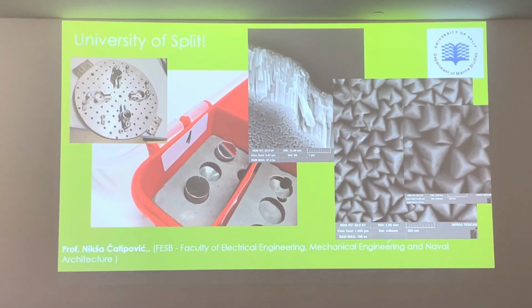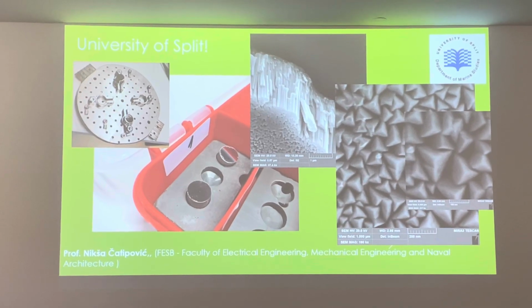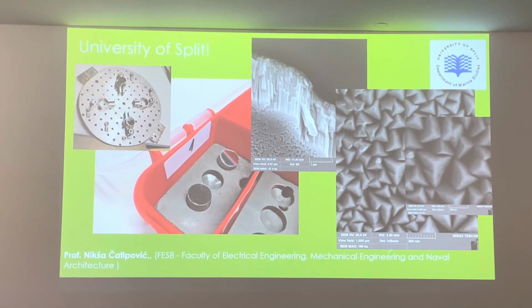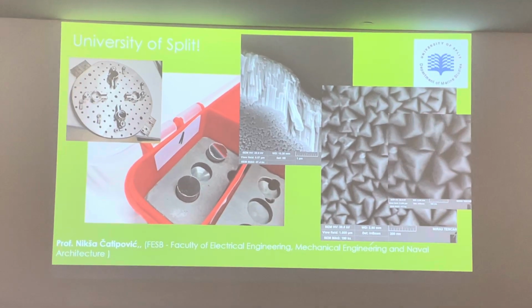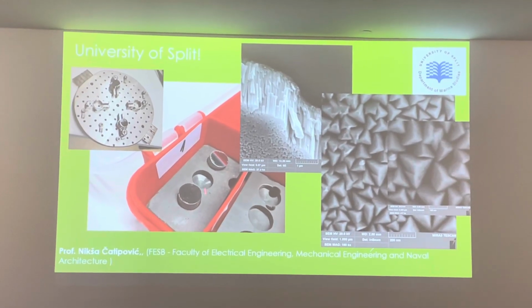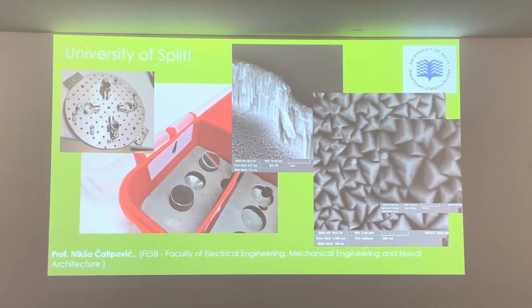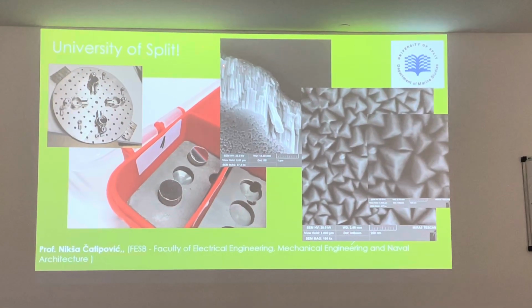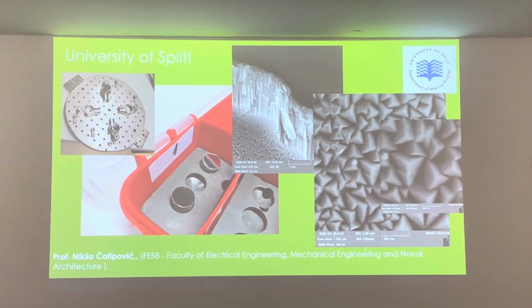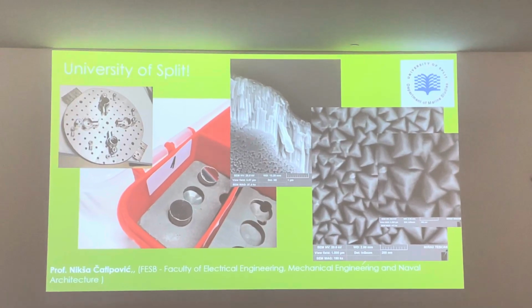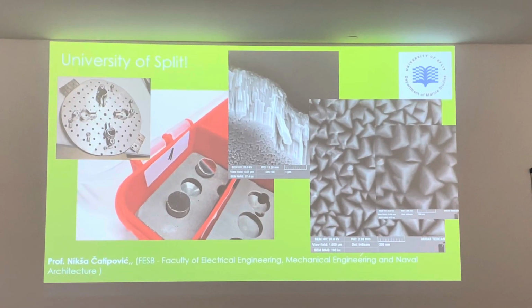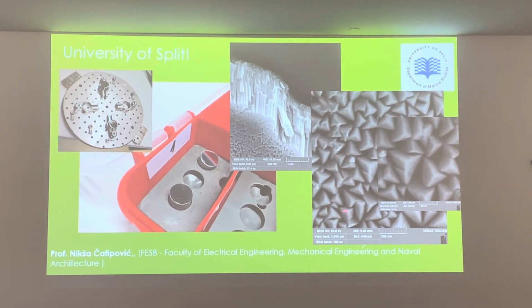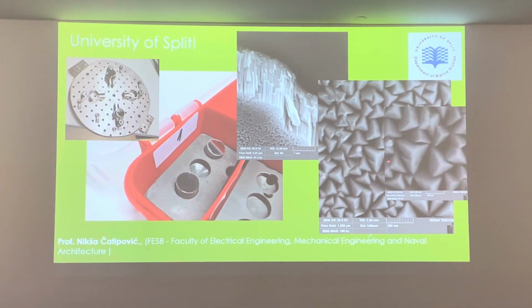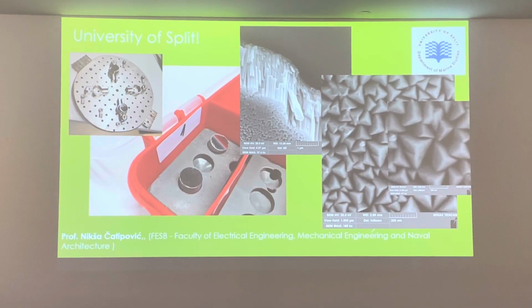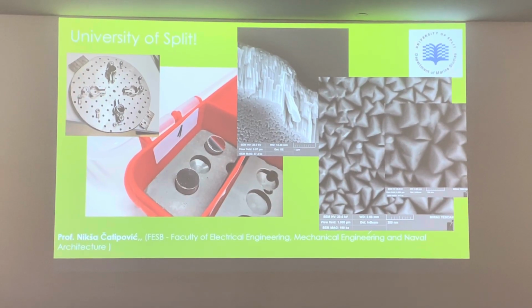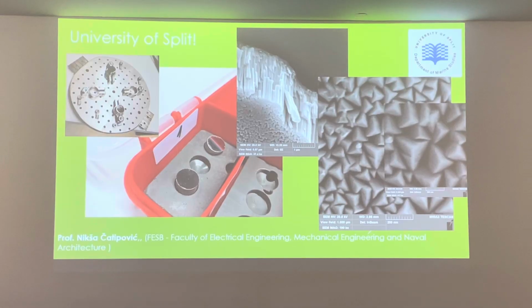And the next application is from that sputtering target, using magnetron sputtering. We have made high entropy alloy coatings on such cylindrical samples. And it is very interesting that the height of this coating is up to 2 microns, with a very fine microstructure with nanometric sizes, with crystallites like pyramids. And these results are from ongoing experiments and research.